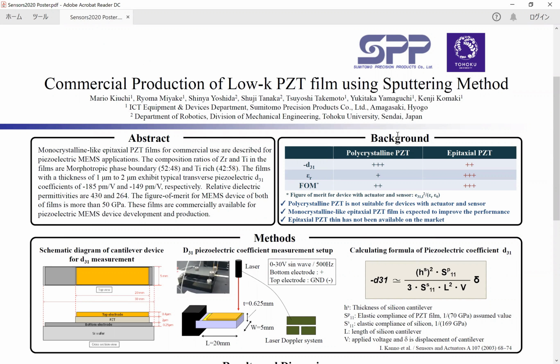Polycrystalline PZT thin film has been widely used for MEMS devices because of its advantage of the large driving characteristics, which depends on its high D31 coefficients. However, it is not suitable for devices requiring not only the performance of actuator, but also that of sensors such as PMUT, due to its high dielectric permittivity. On the other hand, monocrystalline-like epitaxial PZT film is expected to improve the performance of the device compared with polycrystalline PZT thin film because it enhances the device figure of merit or FOM primarily resulting from reduced PZT dielectric permittivity.